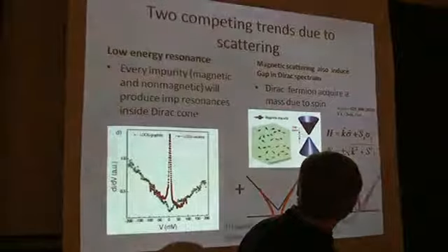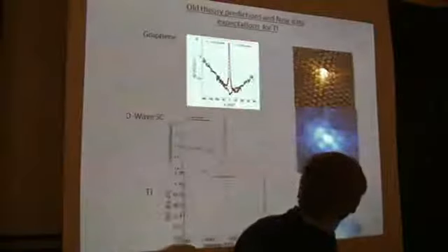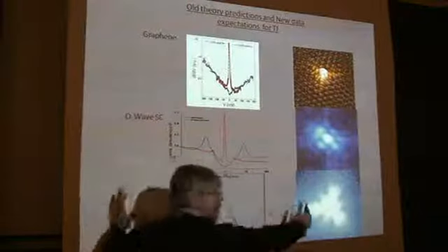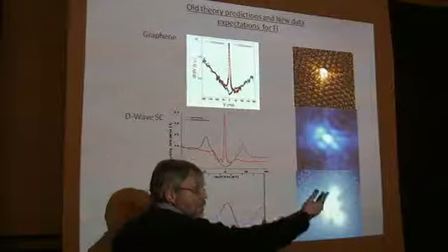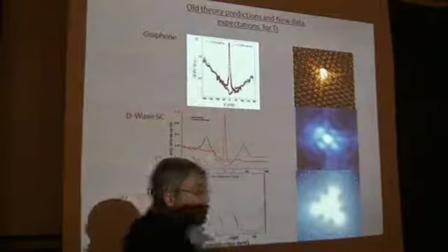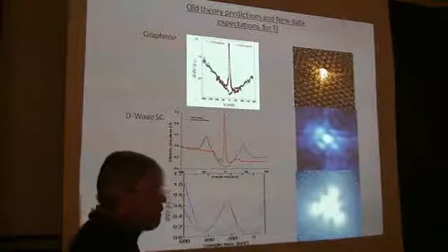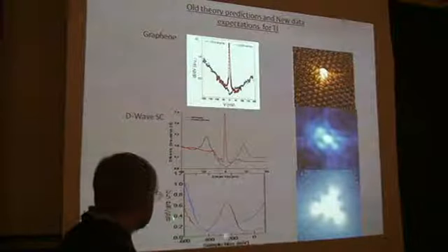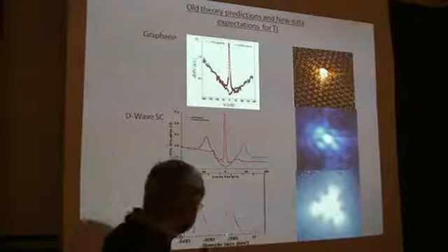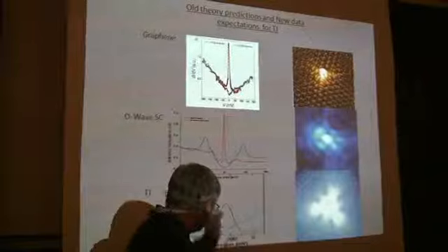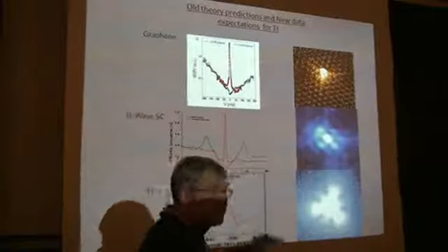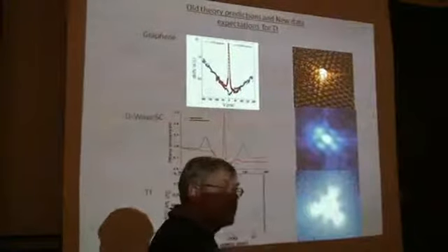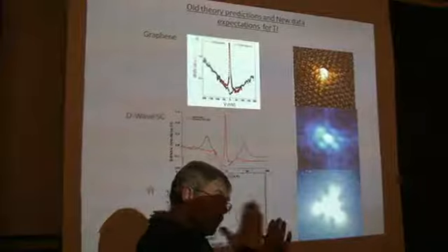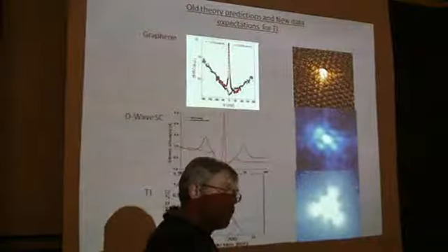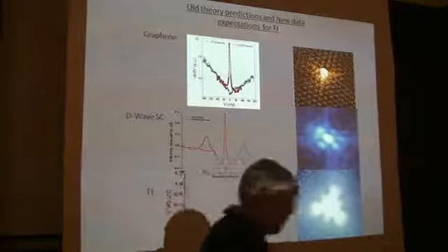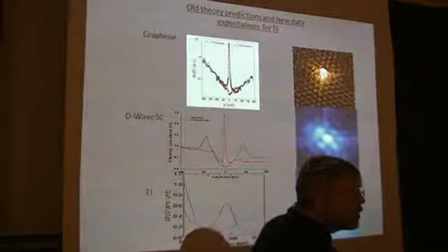So you're taking me off on a tangent here. But basically, if you open up this whole thing, I can show it to you in the papers. There is more than one paper. But you know, this is actually a conventional material. Is the dI/dV the density of states, right? It's a local tunneling conductance, yes. And so the Dirac point is commonly believed to be, unless it's doped, about minus 300 millivolts, which is consistent with this ARPES data. But the dispersion of the ARPES, I don't think, is symmetric either, above and below the Dirac point, even in the immediate proximity of zero energy. Yes.